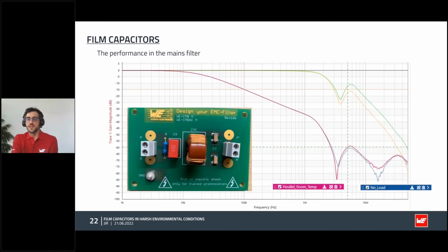Here is another way of representing the result, like the performance of an arbitrary line filter. We measured the frequency response of a filter with the components before the damp heat test and after. In pink, you can see the normal curve as well as the one with the capacitor which was at room temperature. The blue one was in the climate chamber but had no load voltage, so no real difference in the filter performance. The green and yellow components did the loaded damp heat test, and you can see the effect of the capacitance drop. The desired damping of frequencies higher than 10 kilohertz is gone. So the filtering functionality of the capacitor is completely compromised.